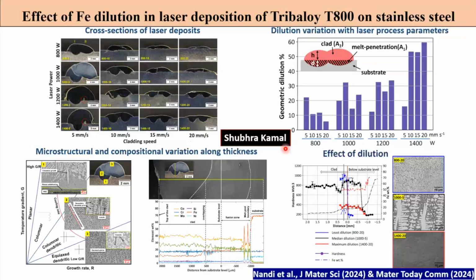Shubhra Kamal is now a joint PhD student between IIT Kharagpur and University of Manchester, and he's currently engaged, and has published a couple of papers first trying to understand the level of iron intermixing and dilution when he deposited Tribaloy T800. This is basically an alloy which produces a large volume fraction of Laves phases, and he is able to prove that by sacrificing a certain level of Laves phases or its volume fraction, he can actually introduce a lot more toughness into the system, which is beneficial.